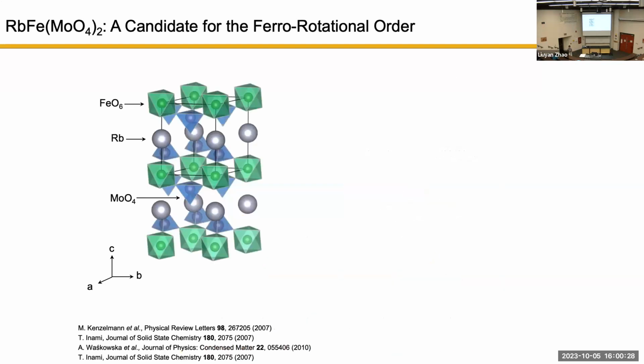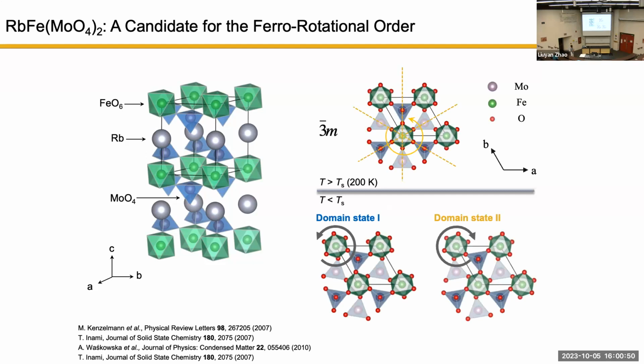So when we started our group, we thought, let's choose a compound that may host this interesting ferrorotational state and use our technique to take a look. The compound we chose is a type 2 multiferroic compound, rubidium iron molybdenum oxide. That's its crystal structure. We pay a lot of attention to its symmetry. At high temperature, it has the so-called bar 3m symmetry, which means we have threefold rotational symmetry, three mirrors that are 120 degrees rotated from one another, and also a spatial inversion symmetry. Those are the generators for the state.